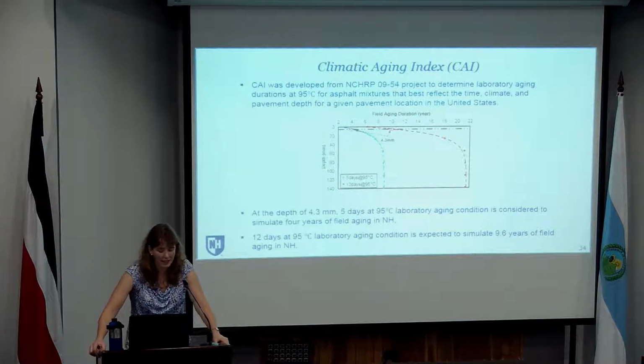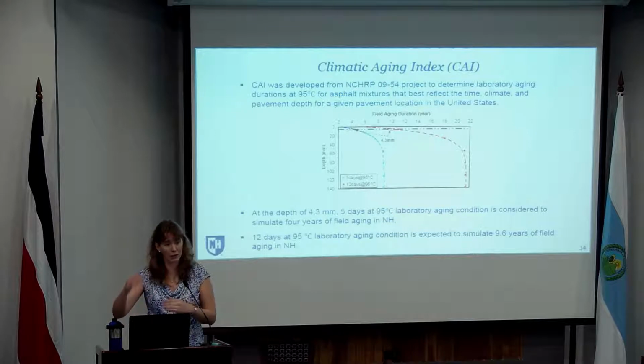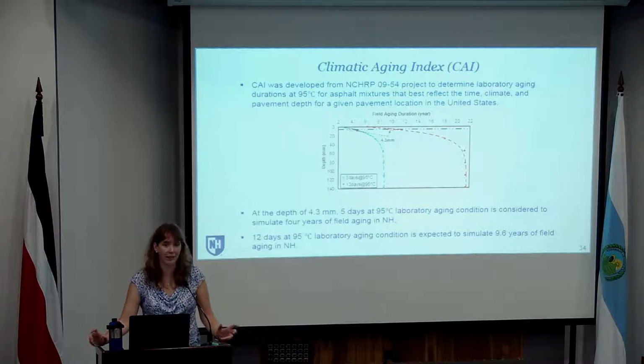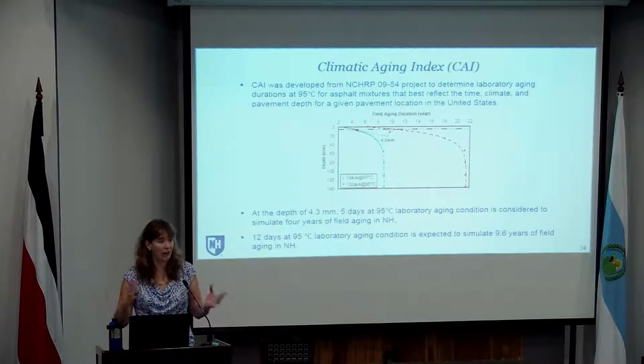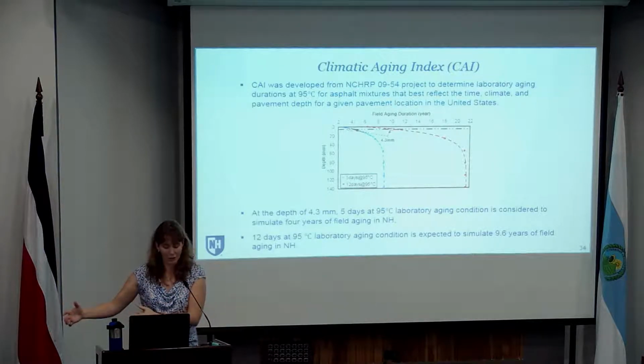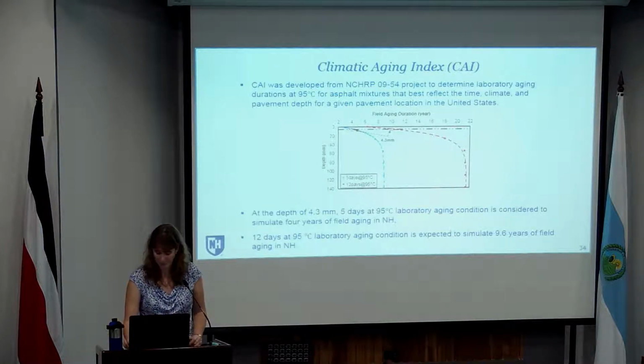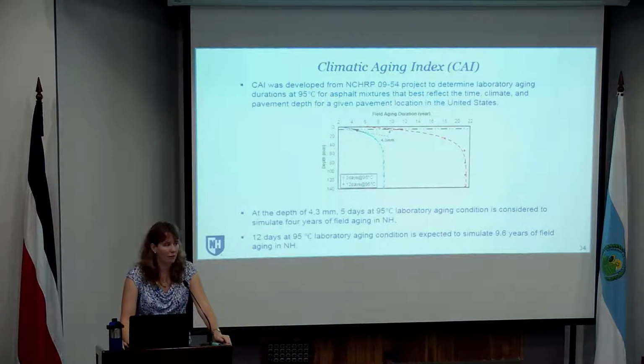And then the 12 days is simulating 9.6 years. So again, that's what we're trying to do: based on that 4 years, establish what the depth is, and then based on that same depth, if we're doing 5 days and then 12 days, what is that 12 days, relatively speaking, doing in terms of the time in the field? So then we've got some kind of feel for, all right, 5 days is giving us 4 years. If we do 12 days, that gets us a little bit more than double the time in the field. And again, we're going to continue to evaluate this over time. So now let's jump into some of the mixture testing results.